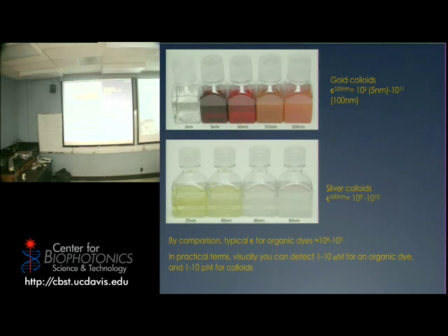It doesn't look like gold, but it is. Gold, you guys all know how it looks. It becomes red because around 520, 540 nanometers, it absorbs light. What's left gives you the impression of being red, and that's how they look. And as you can see, they're suspended, they're transparent, they don't have any interest in precipitating off or anything. And also, because of the resonance, the capacity of this material to absorb light is huge.